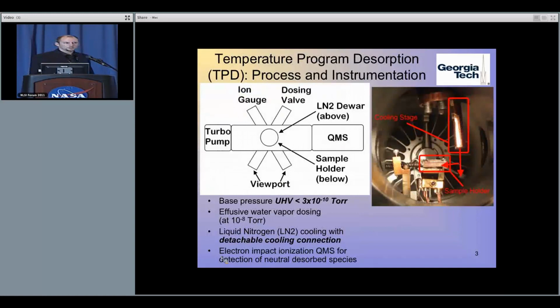A little bit about how we do the experiments. We do have an ultra-high vacuum chamber that we built specifically for these experiments. We have a base pressure in the 10 to the -10 torr range. This is necessary to do these sorts of experiments. You can't even do them in the -9s.